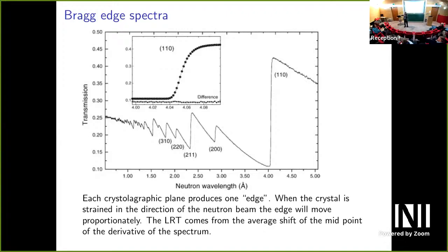So even a fairly smooth strain that's roughly constant over a voxel but changes as we go along the beam, you can think of each of those as having a different separation between the crystallographic planes. So each of them makes its own Bragg edge. And the more volume of strain in that direction of that magnitude, the bigger the jump. So it will broaden this out.